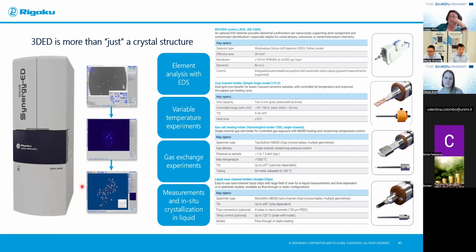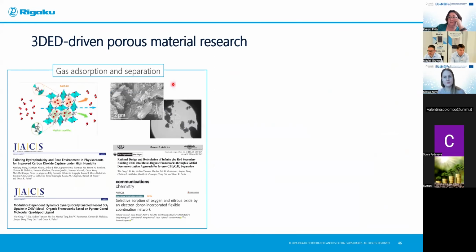not just a crystal structure. It allows you to do, similar to all other diffractometers, variable temperature experiments because of the control, like a gas cell heating holder, which you can see here. You can do gas exchange experiments and measure in situ in the liquid, so crystallization or liquid exchange in your framework. And because the sample is in a vacuum and a small amount, we can provide a basic elemental analysis using the EDS system that is also integrated inside the diffractometer.